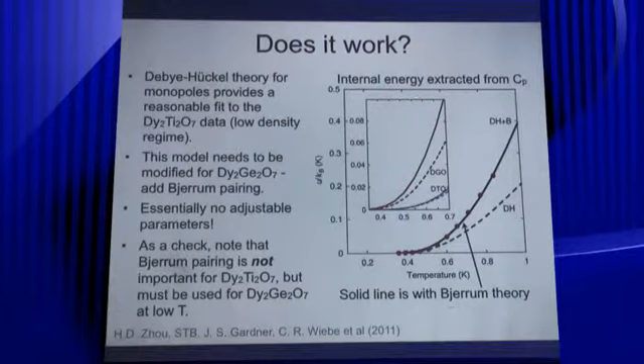So in the inset here, first of all, we have dysprosium titanate compared to dysprosium germanate. The solid line here is the fit with Bjerrum theory plus the Debye-Hückel. The dotted line is just the Debye-Hückel. So as Claudio mentioned, Bjerrum pairing does not make a difference at all for dysprosium titanate. Right? There's only a very, very small difference between these two. However, for dysprosium germanate, it's essential. You get essentially the right fit if you do this.